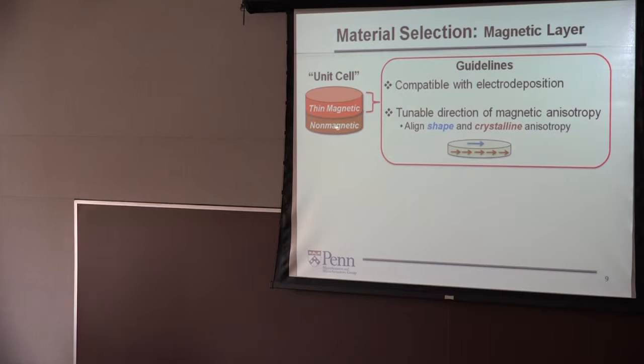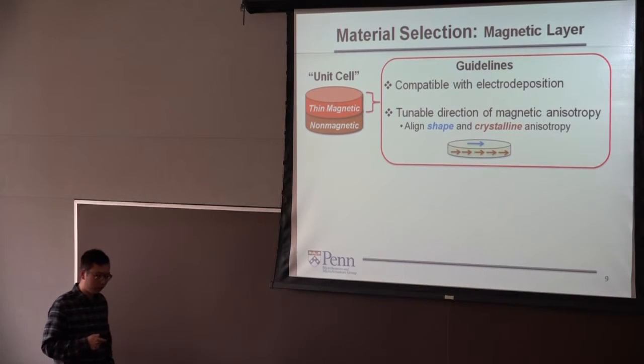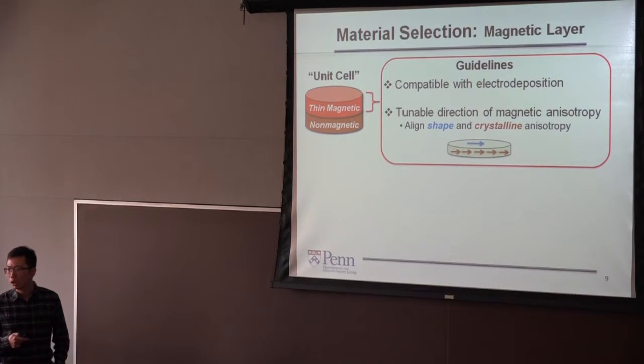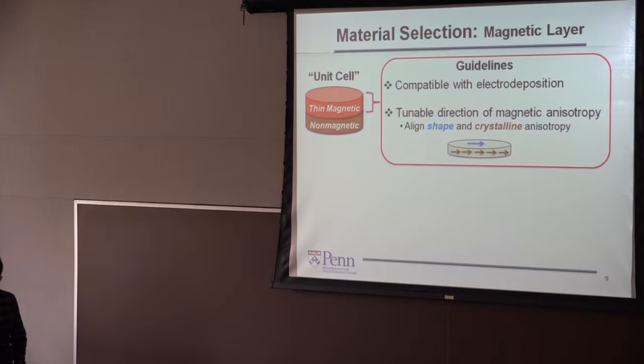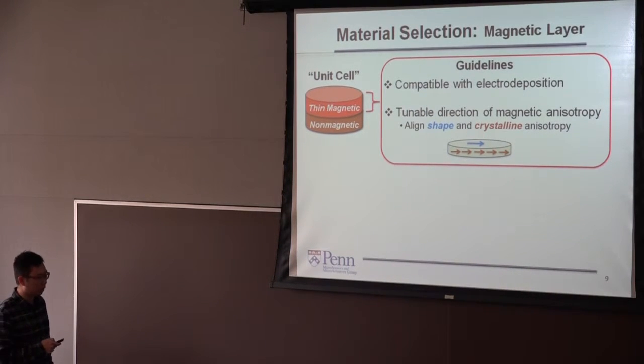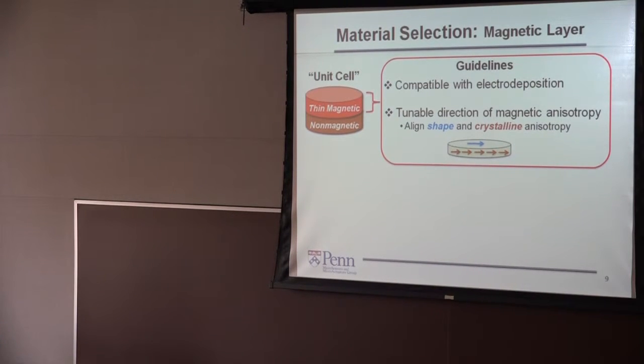First, let's talk about the material selection part. What we call a unit cell of this laminated structure has two parts. First, the magnetic layer. If you want a very thick film, the deposition speed definitely matters. For vacuum-based processes like sputtering, it's relatively low speed, and also less economic compared to electroplating. So what we use here is electroplating, so the magnetic film should be compatible with electrodeposition. Also, very importantly, we would like to tune the direction of the anisotropy in the same direction. For a thin film structure, the in-plane dimension is much larger than the out-of-plane. So the shape anisotropy lies in the in-plane direction. It will be beneficial if we can tune the magnetic anisotropy also in the in-plane direction, so that the overall property is boosted.